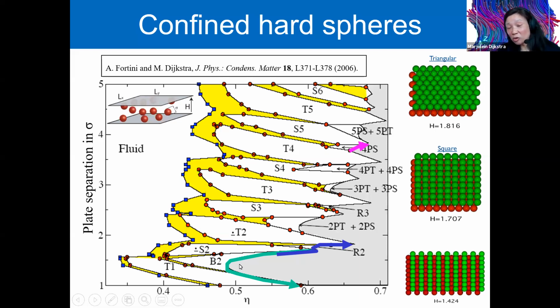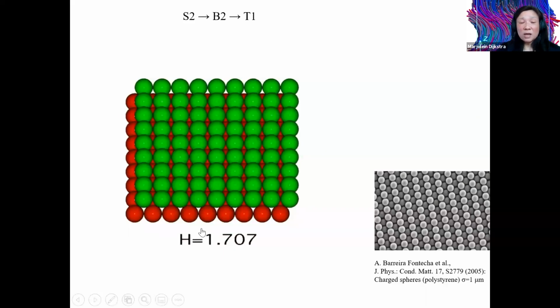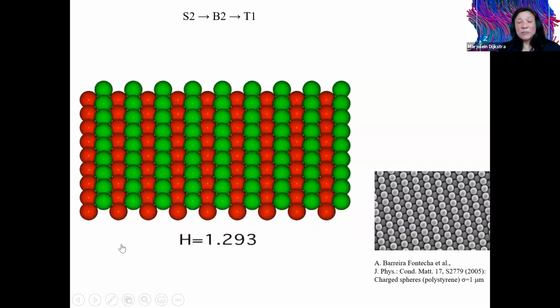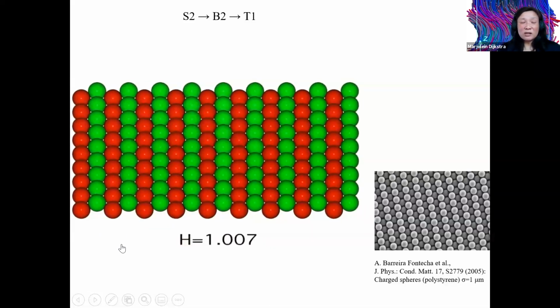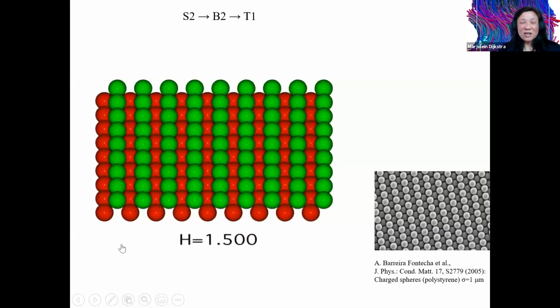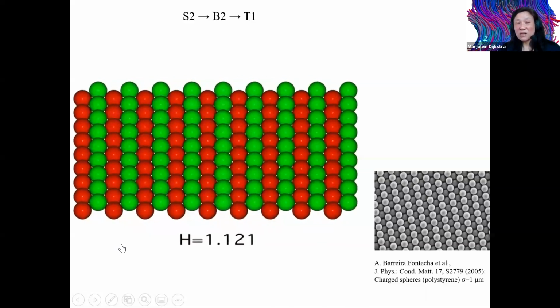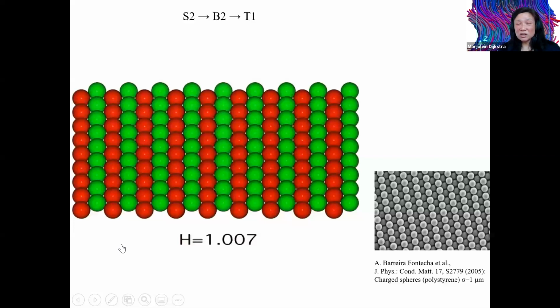So if we take, for instance, the green path where we start with two square layers, we will, if we decrease the plate separation, transform into a buckling state, and then it will form one single triangular layer. And this is shown, for instance, here. It started with two square layers, and then it forms a buckling phase, and then in the end, all the spheres are in just a single triangular layer.